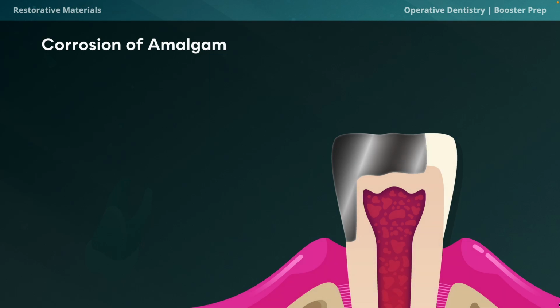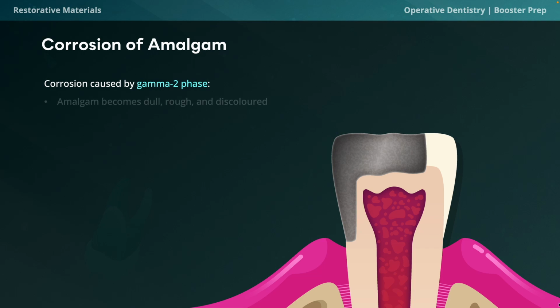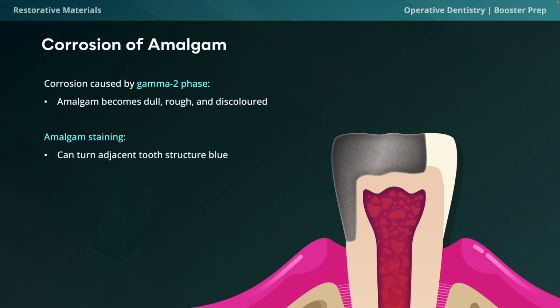Which brings us to the next quick topic of amalgam corrosion. Corrosion is caused by the very same weak gamma 2 phase that we just talked about. So if you have a patient come in with an old amalgam restoration that's looking very dark and dull, it's likely an old amalgam alloy that was not high in copper, and therefore it underwent corrosion. Another sign of amalgam corrosion is staining, which results in a bluish discoloration of the surrounding enamel or dentin. And again guys, if you know your materials, for any new amalgam restorations that you do, just make sure they're high copper amalgam and you'll avoid all of these issues altogether.